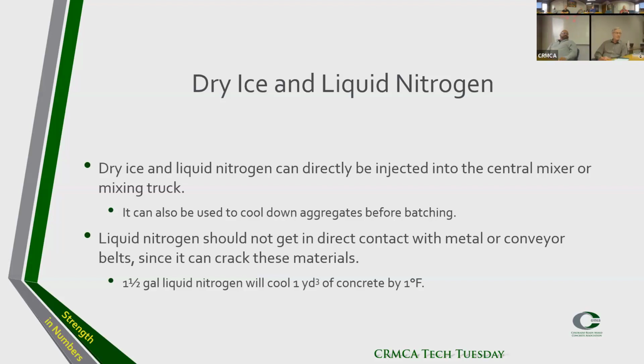Dry ice is CO2. CO2, yes. This should have an impact, no? The dry ice in this case is mainly just to cool down. They're just directly injected in the central mixer. They can also be used to cool down the aggregates. One thing, if anybody ever wants to play with liquid nitrogen: it's dangerous to people. It's going to freeze really fast, and it cracks conveyor belts or metals if it gets in direct contact, because I think the temperature is like minus 180 C. Not sure how much that is in F, but it's a really low temperature, so you have to be really careful. And again, very expensive to use.